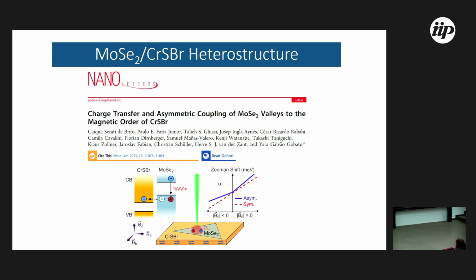Yes. And so I decided, as I was in collaboration with Professor Harry van der Zant, who was working with this material and had the crystals, to make a sample of CrSBr, which has magnetization in the plane, and we put a flake of MoSe2. We were not expecting to have this break of degeneracy, but we decided to measure. And the first thing we observed: there is some calculation that the band alignment between these two semiconductor materials is very unusual. It's a type 3 band alignment, which means that the charge transfer is very efficient in this type of heterostructure.